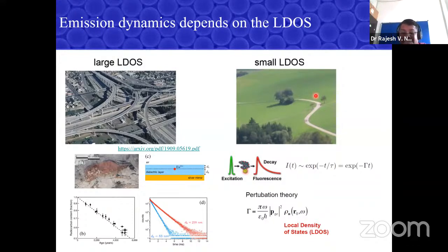So how do you do this experiment? How do you measure the density of states? You have a sample, you excite it, and you measure the fluorescence decay time. If you can measure the decay time or the decay rate, you can relate that, for a given dipole, to the density of states. This gamma, which you get from the experiments, and for a given sample the dipole is fixed, so the density of states can be scaled. And there is nothing great about that in optics.